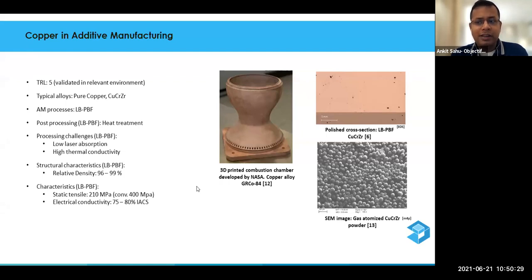Mostly for the space and the e-mobility space, we have been working on this. We are trying to produce it in laser-based powder bed fusion. The post-processing requirements are mostly heat treatment, followed by water quenching. The processing challenge is that it has a lower absorption.